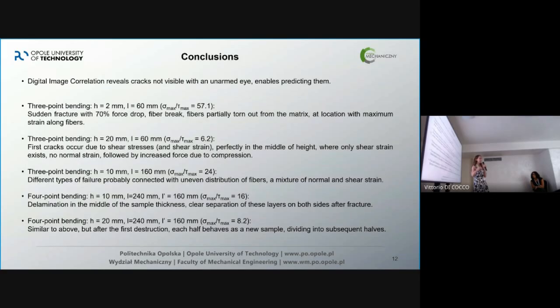And in the 3-point bending, there were different types of failure. And well, I didn't tell you why before it happened, because there were different specimens from different materials. And as I showed you in the beginning, the material had uneven distribution of fibers. So sometimes it was more even, sometimes less even. And if there is uneven distribution of fibers, then when there was just polypropylene, of course it would crack in there. And when there were more fibers in an even way, the material could stand more.